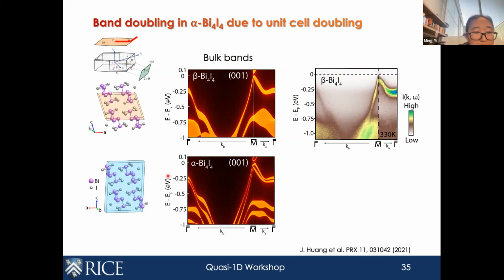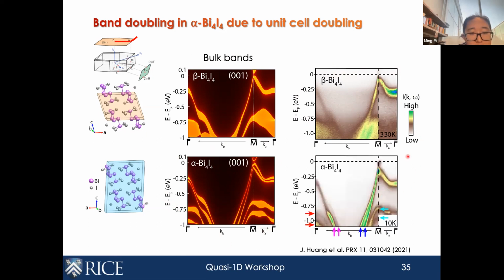Now, if we do the same calculation for the alpha phase, you expect that when you double the unit cell in real space, you fold the Brillouin zone in momentum space, which means the bands would double. And this doubling of the bands is very clear in the calculation, and also very clear in our experiment. So here we point out the splitting with the pairs of arrows, and hope you can see that this is probably the clearest situation, but you can see the doubling of the bands consistent with the calculation, which indicates that the electronic structure indeed follows the unit cell doubling. So that's a good thing.